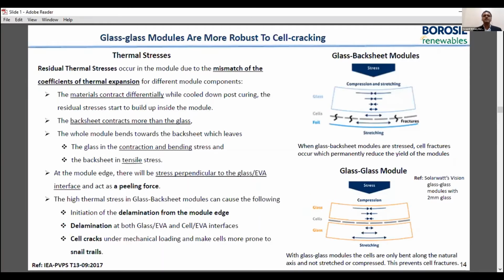So there are certain solutions. Glass modules are considered to be more robust to cell cracking, primarily because of their ability to handle stresses in a better manner. If there are residual stresses, they happen primarily due to a mismatch of the coefficient of thermal expansion and also mechanical coefficients. Glass on the front side and backsheet behind the module have different coefficients of thermal expansion. Especially during module manufacturing or the post curing process, these materials contract and expand differently. When they cure, they contract, and the backsheet contracts more than the glass.